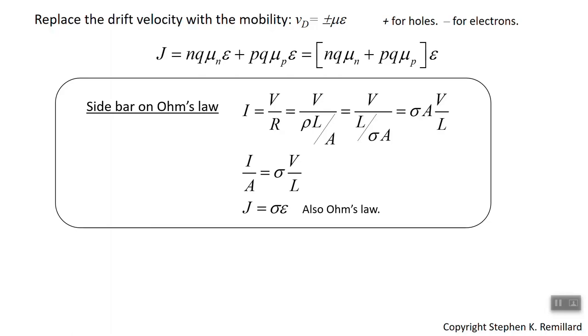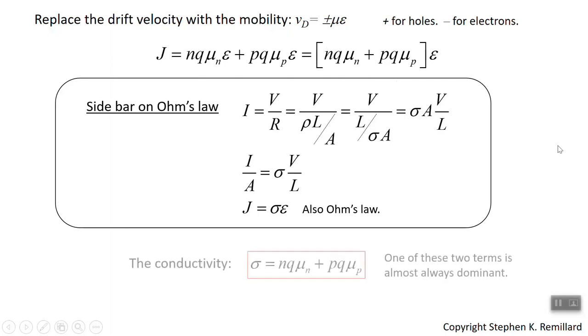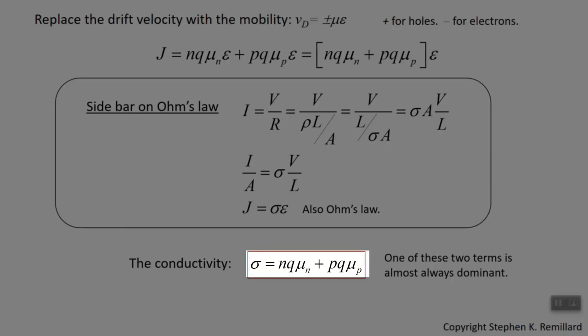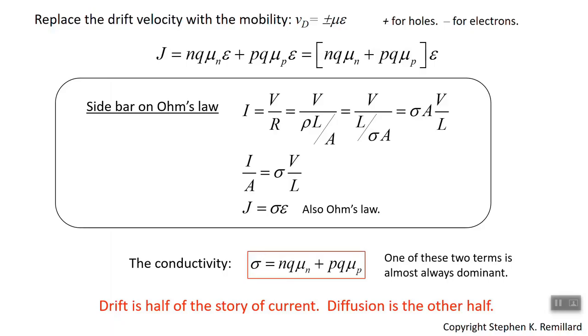J equals sigma E is an alternative expression for Ohm's law preferred in electromagnetism, and only truly Ohm's law if conductivity is independent of electric field. Comparing our derived expression with Ohm's law, the quantity inside the square brackets is the conductivity. The conductivity of a semiconductor is electron carrier concentration times q times electron mobility, plus hole carrier concentration times charge times hole mobility. Typically a semiconductor is either electron-doped or hole-doped, so one term dominates the conductivity and the drift current.